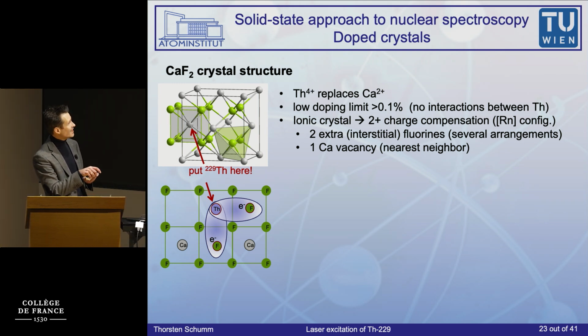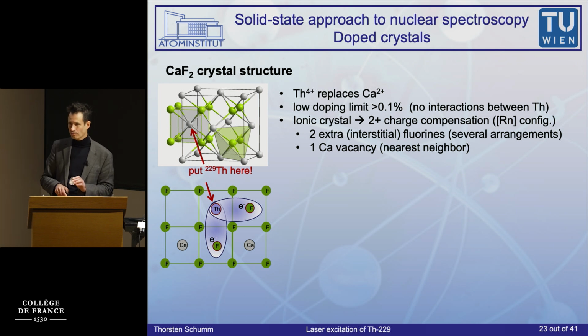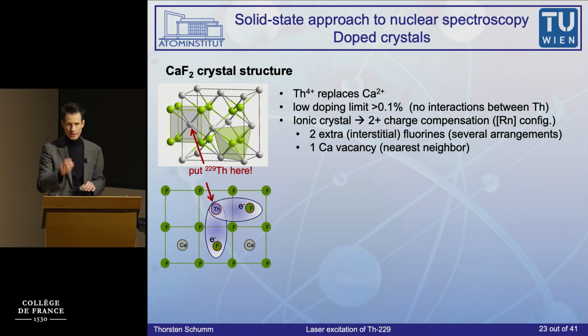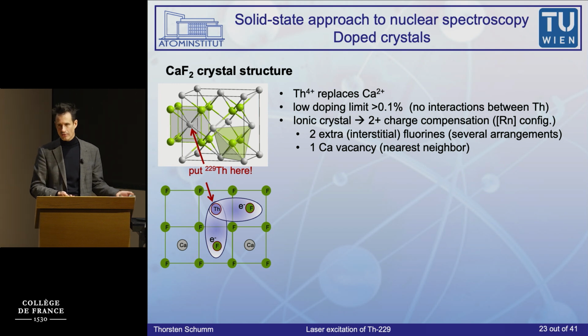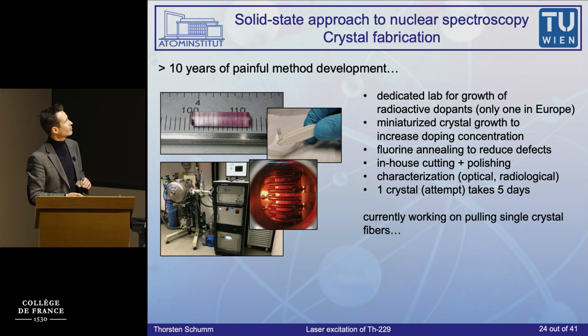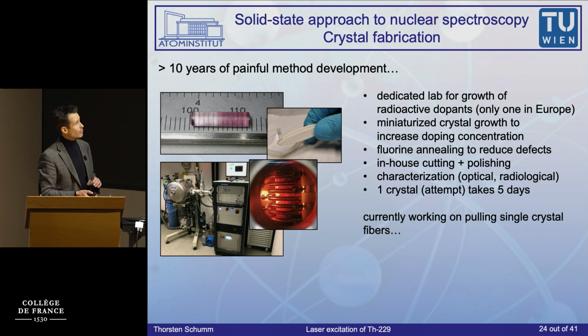Now, how do we get thorium to replace calcium in these crystals? We can't put them in with tweezers. We actually have to melt the whole thing and then do crystal growing. Crystal growing takes place at 1,640 degrees centigrade. This is the temperature at which calcium fluoride melts, and then we do this. We take calcium fluoride. We drill a little hole here. You see this, there's a little hole here.